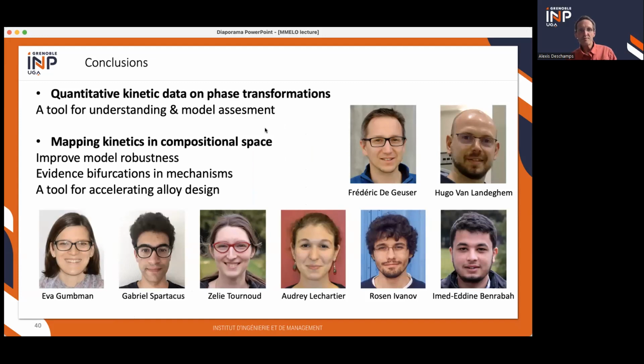And so I hope I've been able to show that having quantitative kinetic data during in situ transformations is useful to understand what's going on. For model assessment, finally, I did not show so much how we could use this quantitative data with models. I could have some more examples, but I was running out of time when I was preparing the talk. And that mapping kinetics in compositional space is able to improve model robustness, can evidence when you have bifurcations in mechanisms, especially in phase transformation trajectories, and then can be used as a tool for accelerating alloy design.